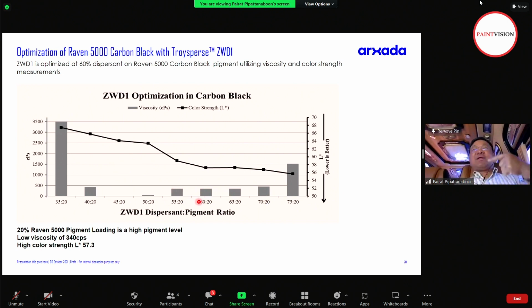So we may focus somewhere around here as the lowest viscosity of pigment paste at carbon black 20% loading, and then we check the color tinting into the white base, water-based system. We see that somewhere here, which is 60% percent on pigment weight at 20% carbon black loading, you get an L value of about 57, right? So it's the lowest L value. With carbon black, a lower L value means a deeper blackness. So viscosity is around 340 centipoise, even though it's not the lowest, but it gives you the best color strength